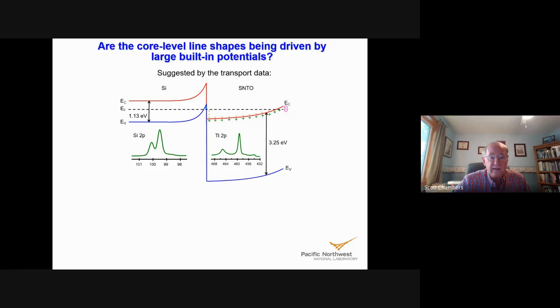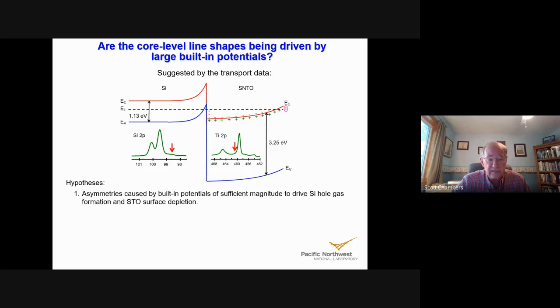If we take a look at what the transport data suggest about the way the band energies vary with depth, they suggest something like this. So we formed a couple hypotheses. One, could the asymmetries be caused by built-in potentials that are big enough to drive the silicon hole gas formation, and also something which is called surface depletion on the STO?